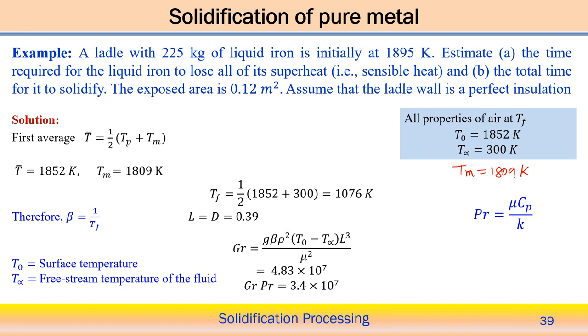Now, we have to estimate the time required for the liquid iron to lose all its superheat. First we calculate the total amount of heat lost by this liquid iron as superheat, that means to go from the peak temperature to the melting point temperature. This is one time count we can estimate. The second one is the total time required for it to solidify, which means we need to count the phase change from liquid to solid at the melting point temperature. Then the total time T1 plus T2 indicates the total solidification time in this particular case. Assume the exposed area is 0.12 meter square.